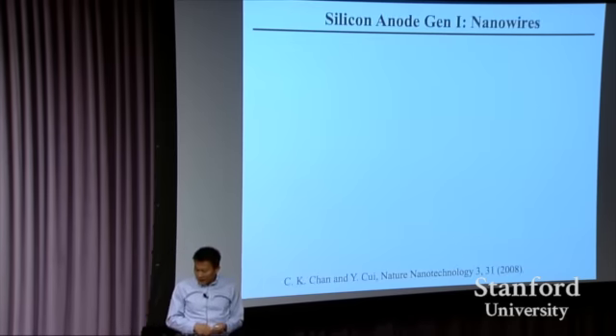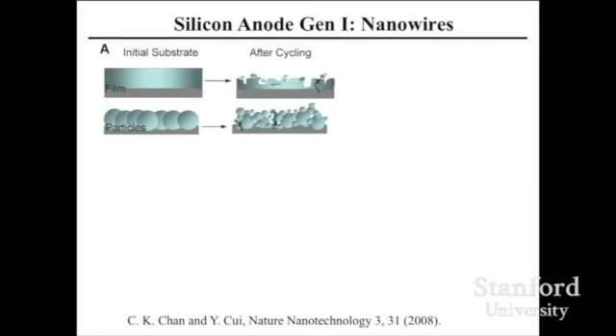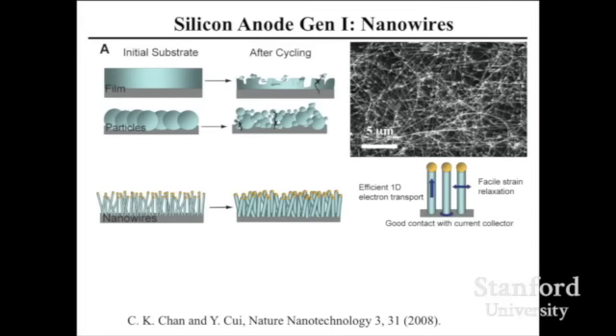Now the first paper I published with a graduate student to really go into battery research is this silicon nanowire. As soon as I learned about the silicon anode problem, this became a natural thinking. Why don't we use a nanowire shape? We know the film and the big particles all break. But the nanowires are small enough. They expand, contract, expand and contract, but their diameter is small enough, with free volume around the nanowire, that they don't break. As the first order of thinking, we went in and tried it. It works. So you can start to cycle your batteries.